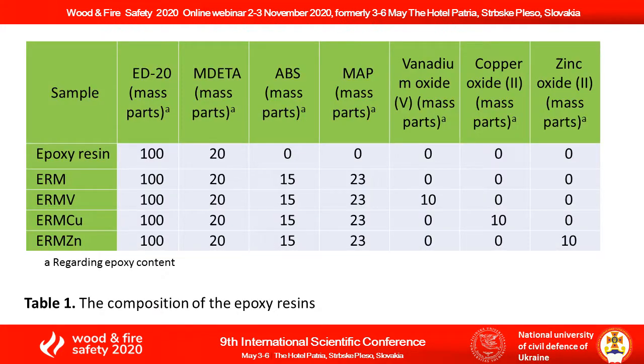Compositions based on epoxy resin ED20, cured by the amine type hardener modified diethylenetriamine (MDETA), were used as a research object. To control the flammability and operational properties of epoxy polymers, basalt scales activated at increased temperatures (ABS) and monoammonium phosphate (MAP) with a particle size of 50-63 micrometers were used, as well as transition metal oxides as modifying additives: vanadium oxide, copper oxide and zinc oxide. Researched compositions of epoxy resin are presented in Table 1.